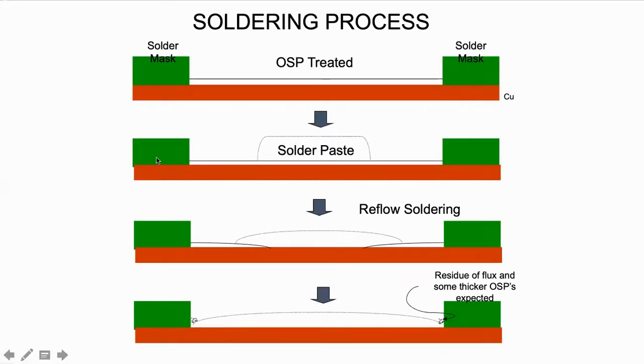Now, as you know, we've said before, OSP is an organic coating. And it's only a temporary coating. In other words, during the process of assembly or soldering, when the fabricator either goes through wave solder or printing solder paste for reflow, the fluxes both in the solder paste and in the flux, once it becomes activated, will remove and dissolve the OSP film. And as the OSP film dissolves, it allows the solder to spread and make complete contact with the copper surface. This is different than, let's say, immersion gold over nickel, where the gold actually dissolves in the solder. In this case, OSP just completely dissolves and basically is, if you will, sublimed into the atmosphere, and no longer stays with the solder joint that has been formed. So there are some differences here.